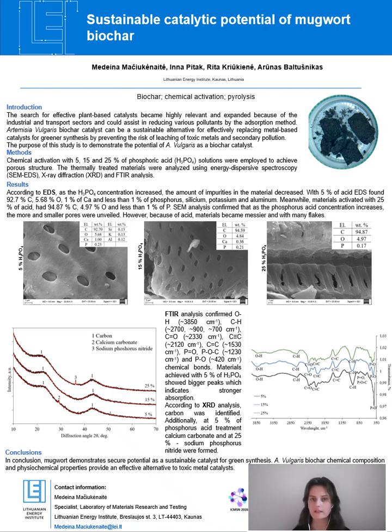SEM analysis confirmed that as the phosphoric acid concentration increases, the more and smaller pores were unveiled. The activation process enhanced more pore formation and increased the overall porosity of the activated biocarbon. And these properties may improve adsorption performance due to the greater availability of active surface sites. However, at higher phosphoric acid concentrations, the material structure became noticeably more irregular and disordered. Excessive chemical activation likely caused partial destruction and fragmentation of the carbon, and it resulted in a heterogeneous and less structurally uniform material. FTIR analysis confirmed chemical bonds between oxygen, hydrogen, carbon, and phosphorus.